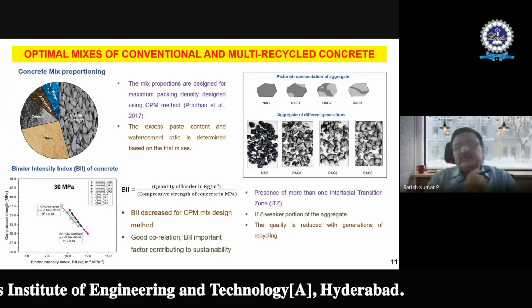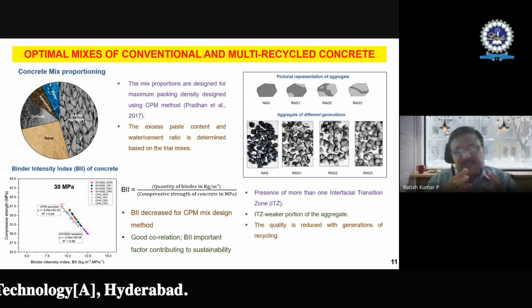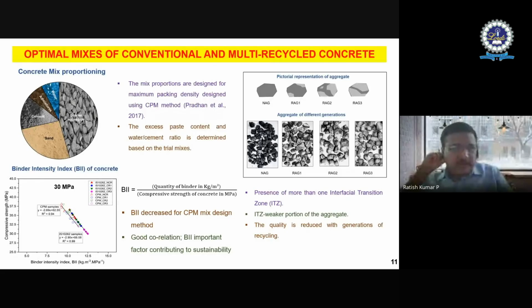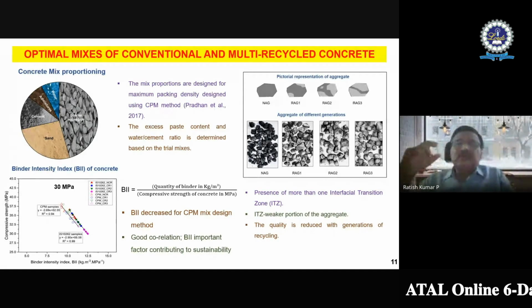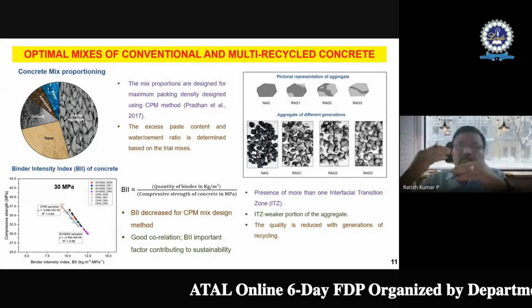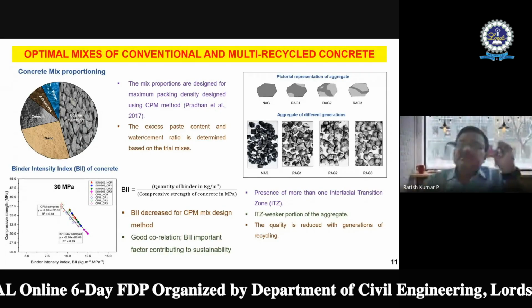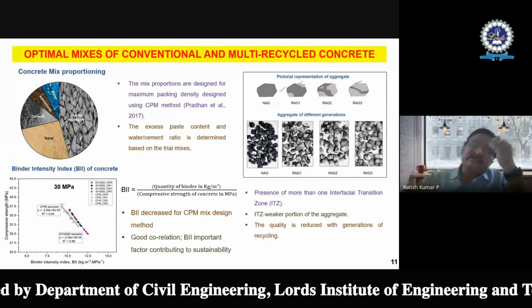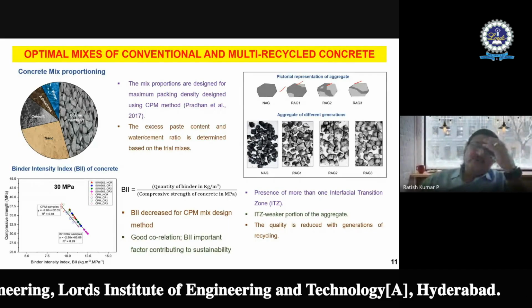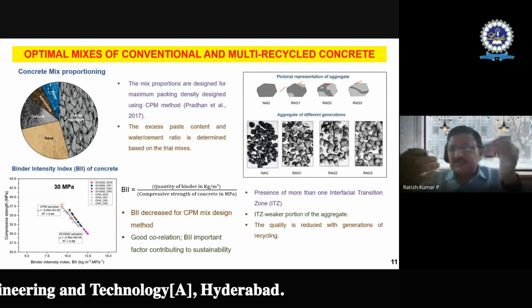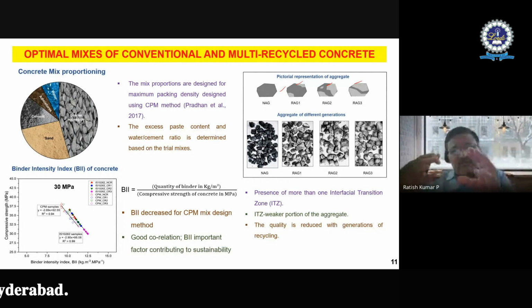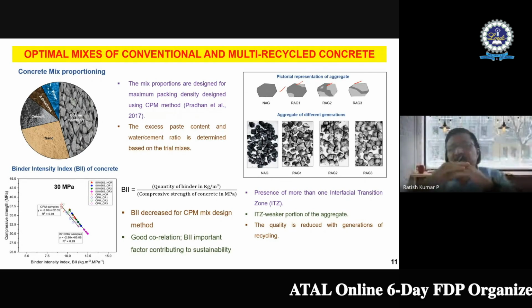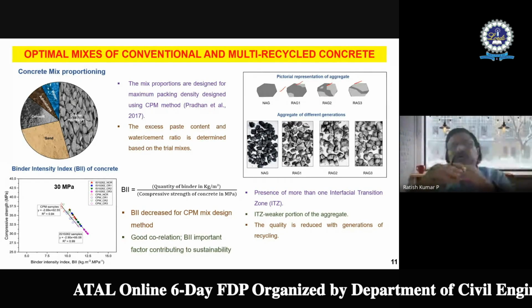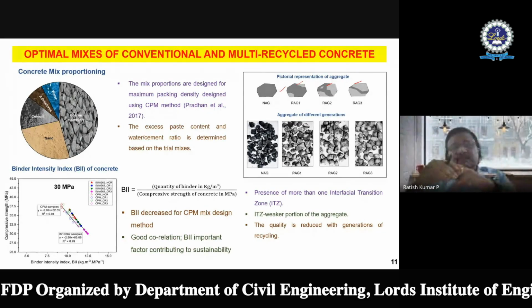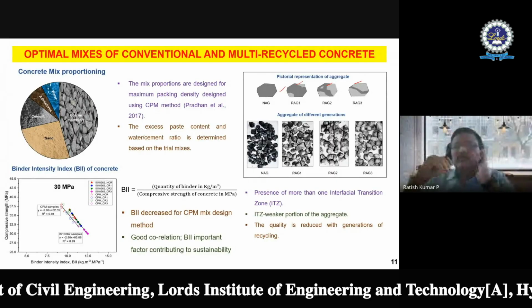Now, let me try to see there is one disadvantage or one serious problem in the case of recycled aggregate, and more so in the case of multi-recycled aggregate, because as you can see, the paste content or the old mortar, which we call adhered mortar, is going to increase as the generations of recycling increase. And obviously, when you do the jaw crushing, which I proposed earlier, the adhered mortar will be removed, and there are certain other methods also which I mentioned. That we have the thermomechanical treatment or mechanical treatment or simple soaking method or acid treatment. These are some of the methods which are actually there, so we can also try them.